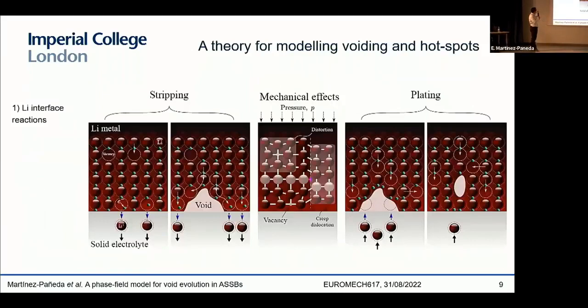So there are many things happening here. One thing, as we already discussed, is the interface reaction. So we need to capture the fact that whenever we have stripping, we have lithium that is being removed from the lithium metal anode and going into the electrolyte. And whenever we have plating, whenever we have charging of the battery, then we have lithium that is being deposited on this lithium metal anode. So that is one key element that you need to capture, these interface reactions.